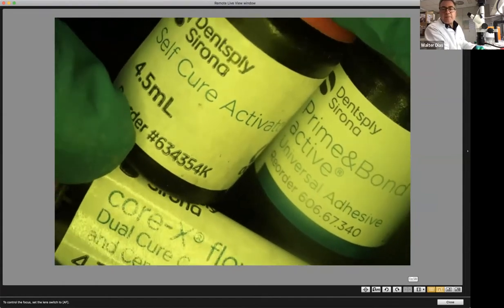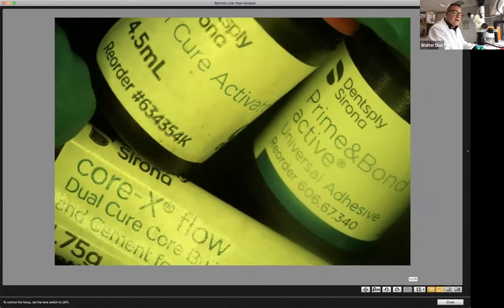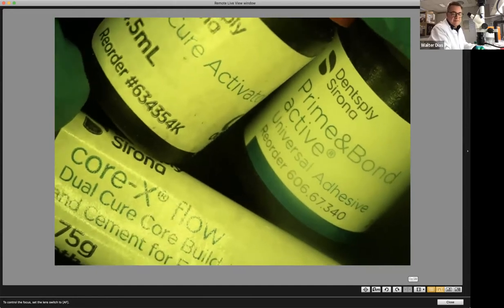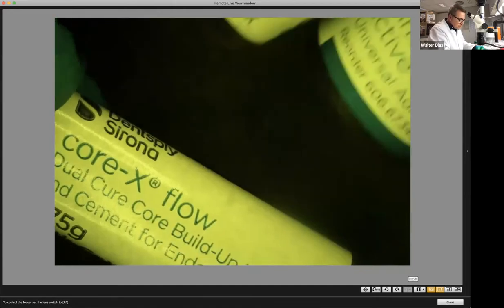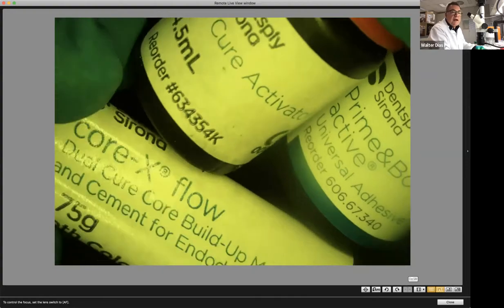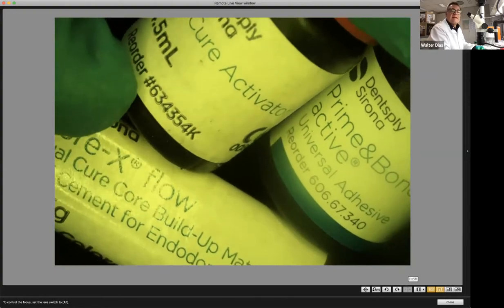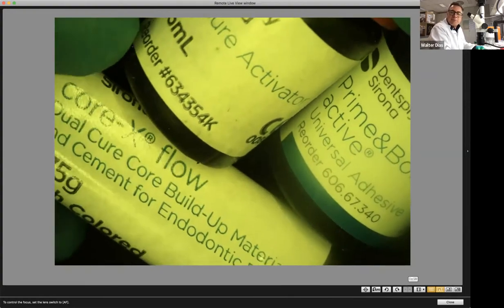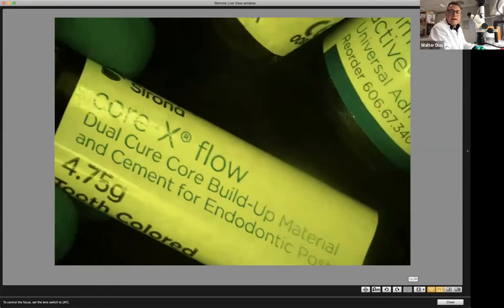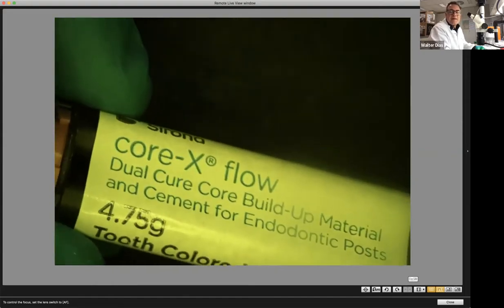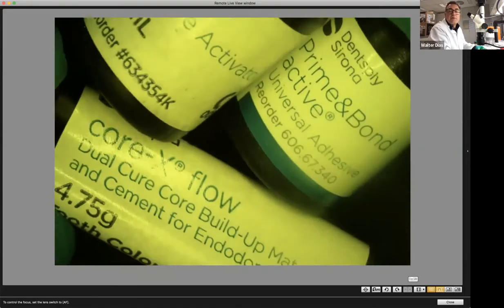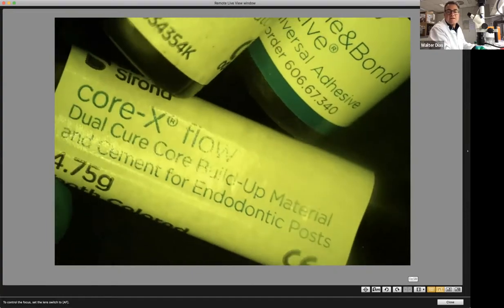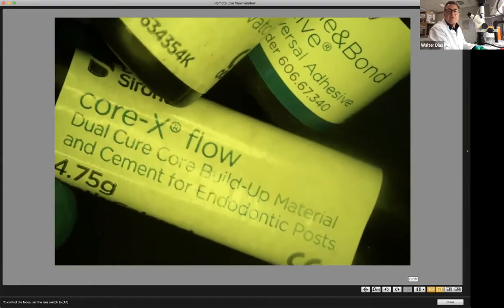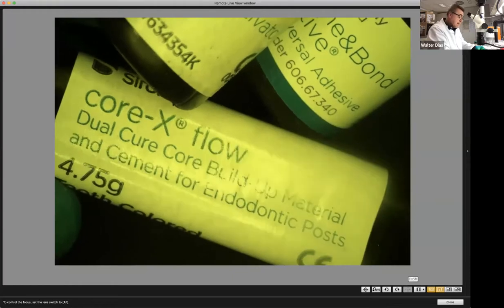Imagine a post cementation, for instance, or a large core buildup, and things like that. So for cementation of crowns and veneers, this is not really applicable, because Core X Flow is a core buildup cement. But for the cementation of posts, it's a dual cure buildup material and for cementation of endodontic posts, it's ideal.